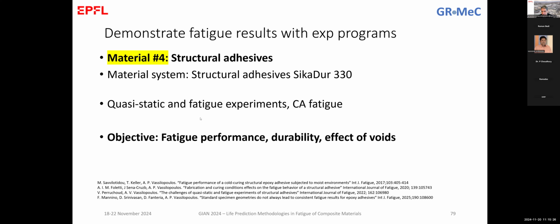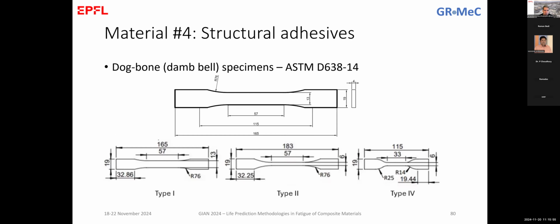initially on the properties of the adhesive, but also at the next stage on the properties of the adhesively bonded joints. To give you an idea, here I have some references starting from 2017 until even lately 2025. This last publication is already online. And we also have investigations on structural adhesives starting in 2010 for their durability performance. So here I will come back to the discussion that we had regarding the standards. So the ASTM standard suggests this specimen. Actually, this is what is called the specimen type 1.